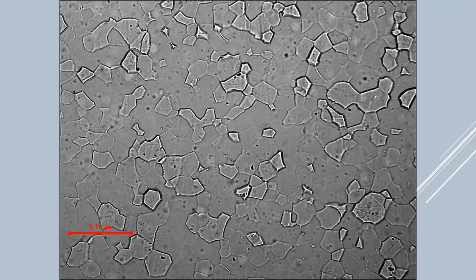Now I ground off about 10 thousandths of an inch because I want to make sure that this is not due to decarburization. You will get some decarburization at the steel mill, but once you go down to that depth, no, this is a rim steel. And the only thing the client has to be aware of now is to operate it correctly. It means the steel is susceptible to a brittle fracture. You load it slowly. Maybe you don't do a hydro test at low temperatures. Maybe you have some sort of management of change notice so that people understand what the problems are with that vessel, and you'll be fine.